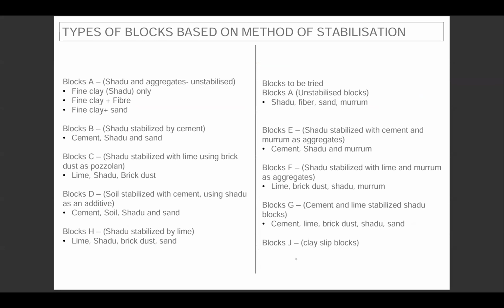So going ahead, this is how we structured what we are going to test. Broadly, the first set of testing we did was to understand a baseline of how the shadow clay is behaving. Those we named as blocks A, which is essentially clay, then one block with clay and fiber and one block with clay and sand, to see how it responds when it dries or when it is tested. Then we did add some blocks. B was essentially stabilized shadow blocks, similar to what Yogananda sir presented earlier.